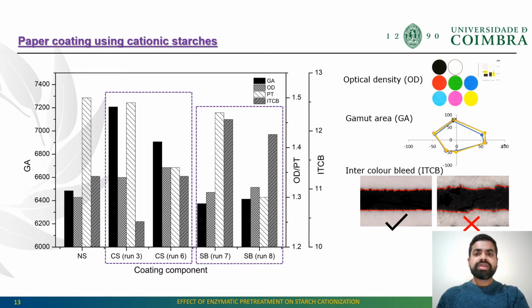The high gamut area in run 3 can be understood by the high viscosity, which plays a very important role in preparation of the coating formulation. Comparing the CS in run 3 and CS in run 6, the gamut area increased for cationic starch obtained from native starch, whereas optical density and print through were better for cationic starch obtained from the cooked starch. The optical density and the print through followed the applied cationic substances on the paper surface and improved with the increasing DS of cationic starches. However, a significant improvement in optical density and print through was reported using cationic starch in run 6.